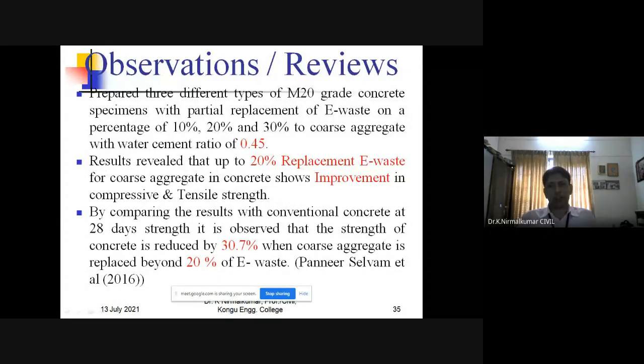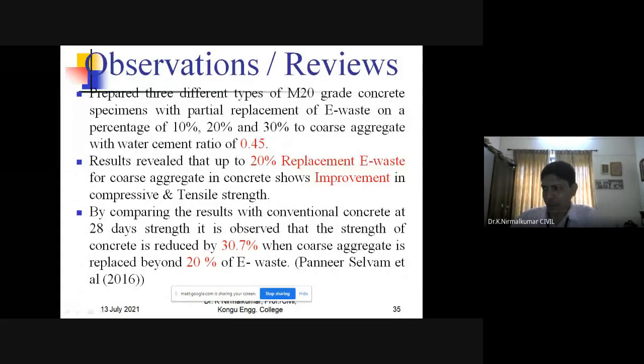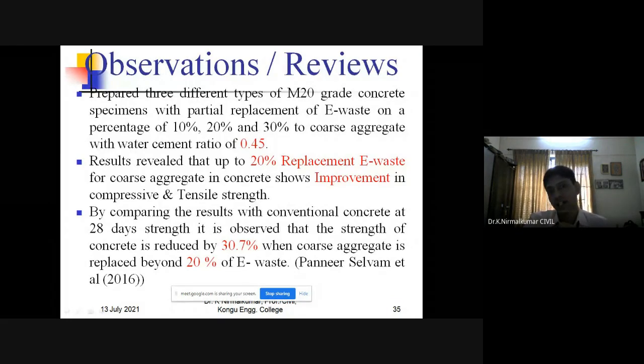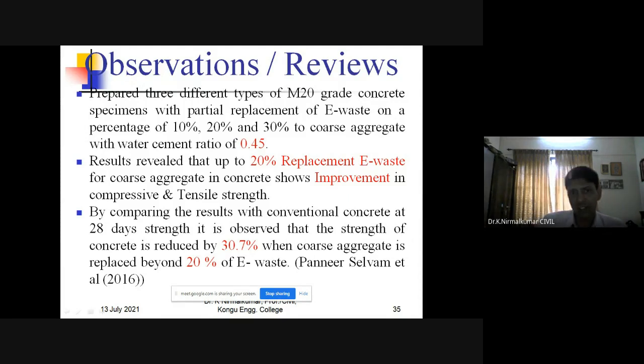Now we are going to see the experimental results. This particular experiment was carried out by Panneerselvam et al. in 2016. He prepared different M20 grade concrete specimens with partial replacement of coarse aggregate by e-waste at 10%, 20%, and 30%, with a water cement ratio of 0.45. He gave the results up to 20% replacement of e-waste for coarse aggregate in concrete.